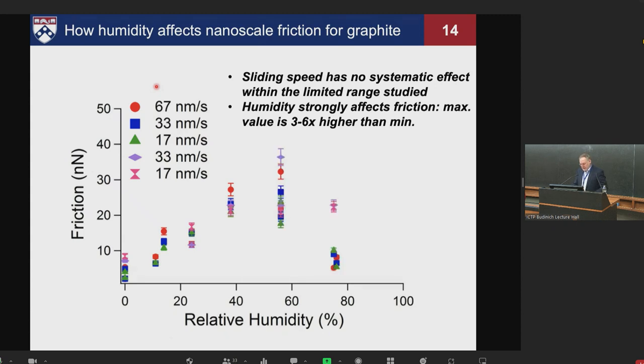But then this happens. It turns over. As you go to very high humidities, closer to saturation, the friction comes down again. This has been seen with adhesion measurements on various surfaces in many cases, and this is still consistent with the capillary model. When you have a capillary and you get near saturation, the larger the capillary, the less the curvature is. Very high curvature leads to a high Laplace pressure. If it's not very curved, you don't have that much Laplace pressure. And if it's just flooded, if it's 100%, if you're just underwater, there's no capillary anymore at all. So the effect of the adhesion goes down.